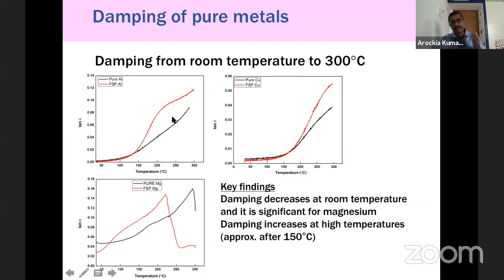So in all these cases, you can immediately come to a conclusion that at high temperature, FSP materials are good in damping the vibration. And this is because of the large fraction of grain boundaries. Generally, grain boundaries are amorphous in nature. So under external loading conditions, these boundaries will move and thereby absorb the external vibration.